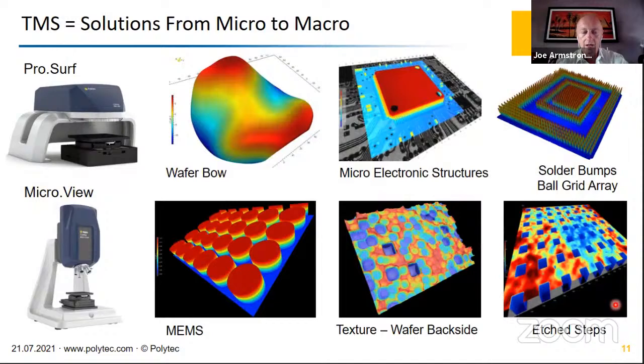Now with our products, it's nice to say different instrument formats suit different applications. So if you are looking at wafer bow, the ProSurf naturally has a larger measurement area and will suit the flatness measurement of a wafer bow. It will suit the inter-surface relationship of maybe a microstructure. It can do larger area counting. So if you want to look at solder bumps, you can do that as well. Whereas when you want to look at maybe more fine details, such as maybe on a MEMS device, maybe a surface texture or a small etch surface, then you'd look at the microscope type system.